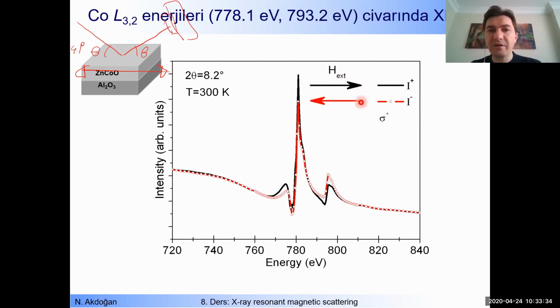So we apply magnetic field along the positive side, let's say, okay, this is the direction of the external magnetic field applied in the film plane, and then we change the energy range. So we scan the energy range, and then we record the intensity at the detector, okay? So intensity is recorded here. So then here we have intensity plus, shown by the black color here.